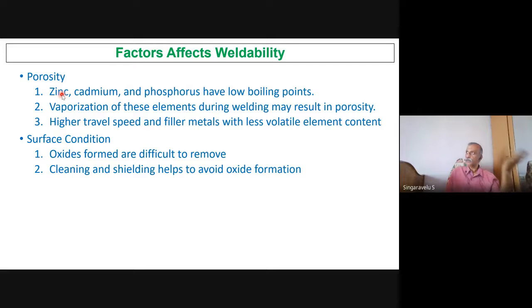Zinc vapor, okay? High travel speed and filler metals with less volatile element content is the required solution. Surface conditions: oxides formed are very difficult to remove. Cleaning and shielding help to avoid the oxide formation. Okay?